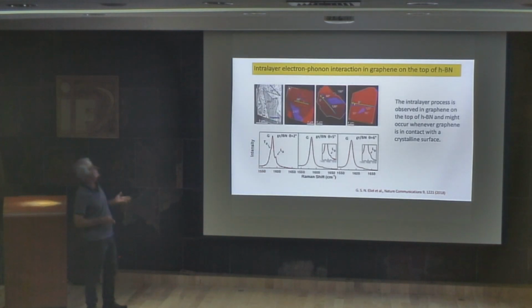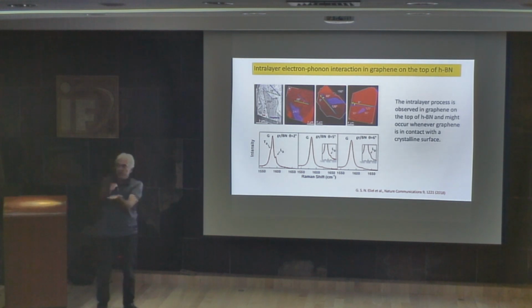Okay, and after that, what we did, we put graphene on top of HBN. HBN is hexagonal boron nitride. Then we can put graphene, and we can also study the angle between graphene and HBN. And we could show that even in the case of graphene on top of HBN, we can see the appearance of those side bands. And those side bands are a signature of the intra-layer process.